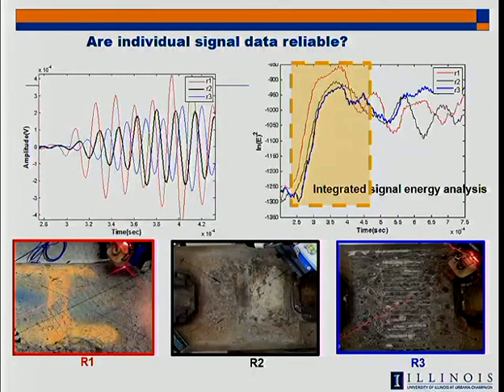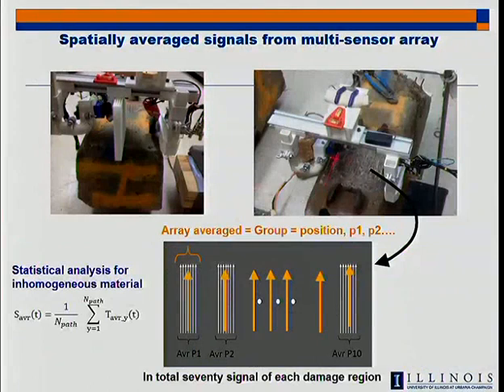And you can see, as we expected, that the more damage that's in there, we have this curve slightly moving to the right. Again, this is with the forward propagating waves. So we do get some sensitivity to that. It's not a tremendous amount of separation amid the noise. We separate these curves, but in some places it's not a clear distinction. It's not enough for us to give confidence. Backscatter, maybe we can find that difference.